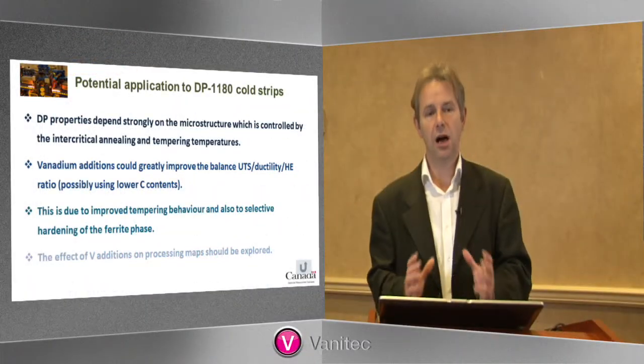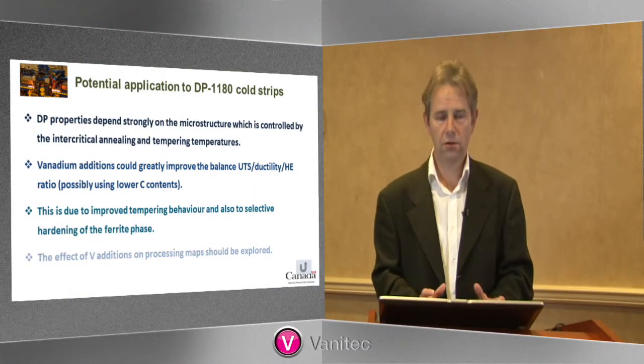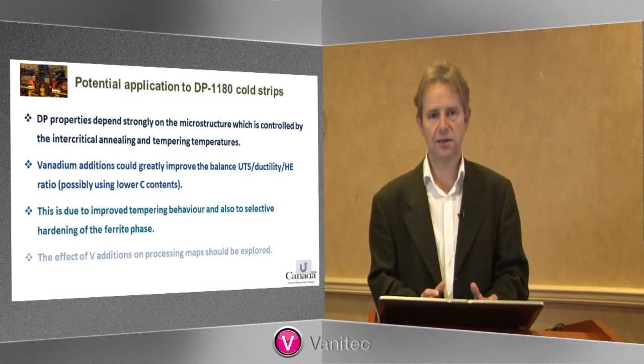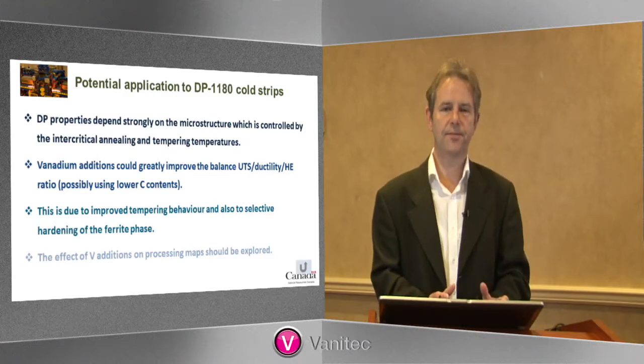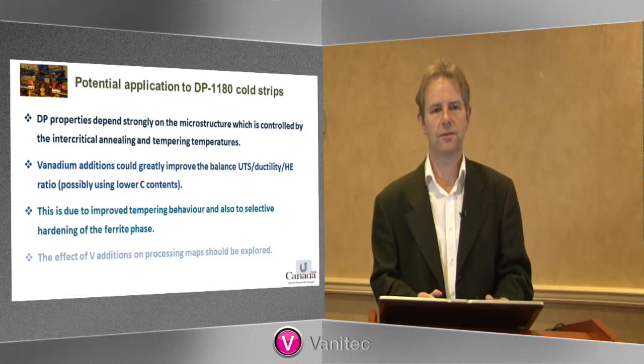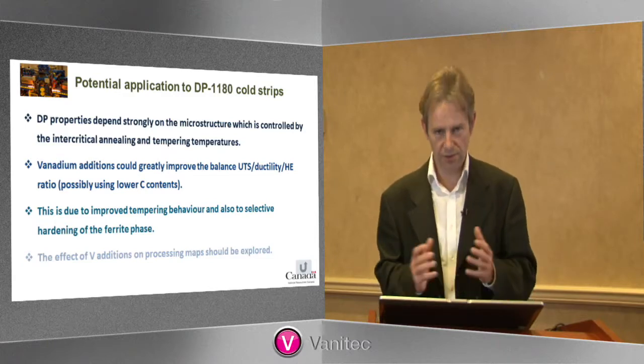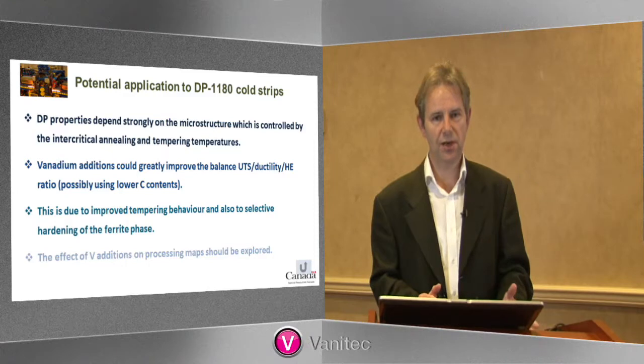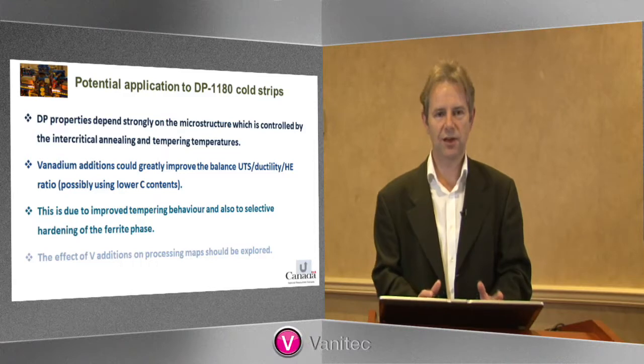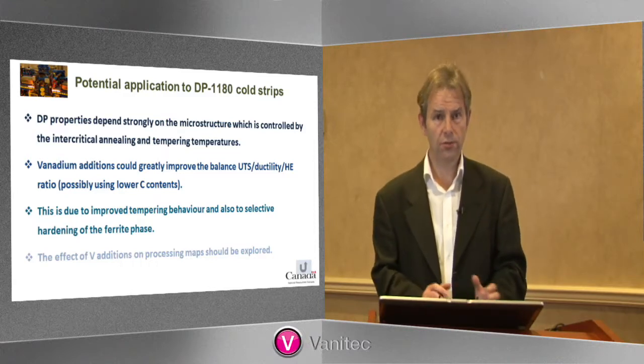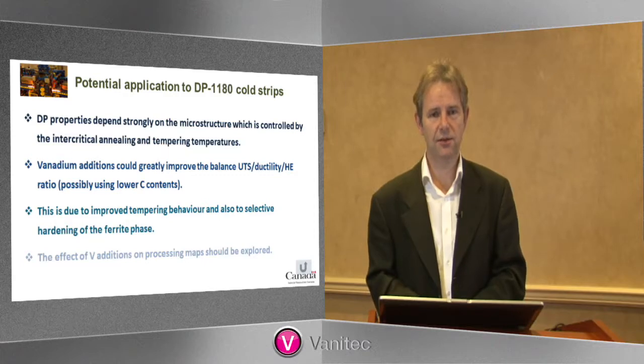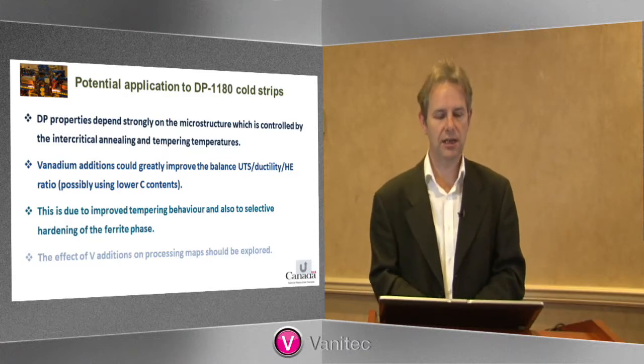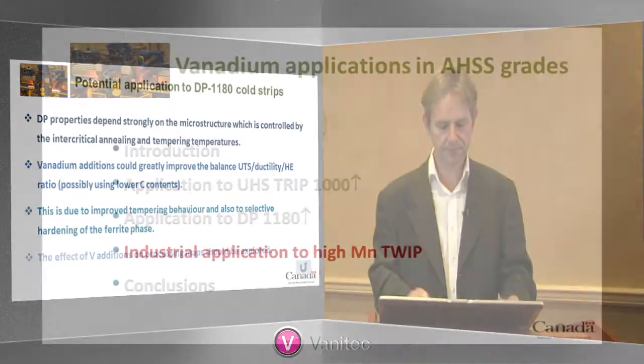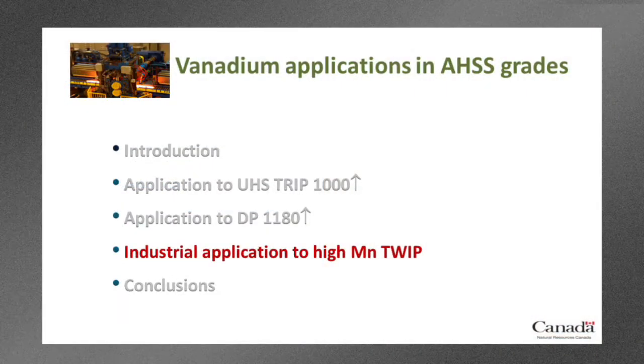First, we could make higher strength, higher ductility steels, or we could keep the same strength and ductility ratios and damage ratios, but use a lower carbon content, which would make the steel more weldable, for example. The reason for those improvements would be improved tempering behavior in martensite and also selective strengthening of the ferrite phase. So I believe very strongly that the effect of these vanadium additions on processing maps is something that should be studied, and we hope to be doing that next year in a project at the CanmetMATERIALS laboratory.